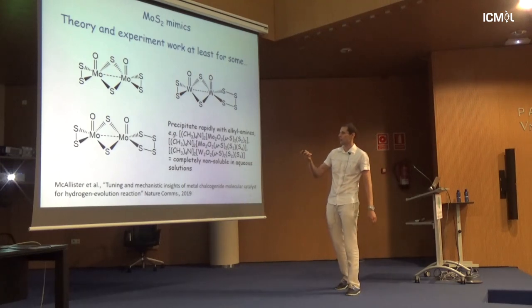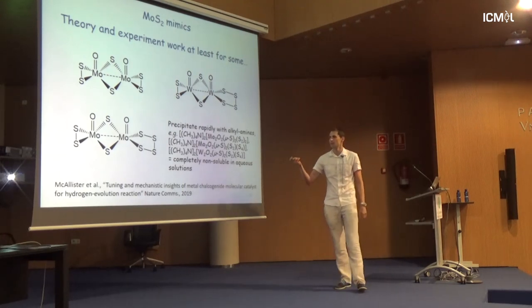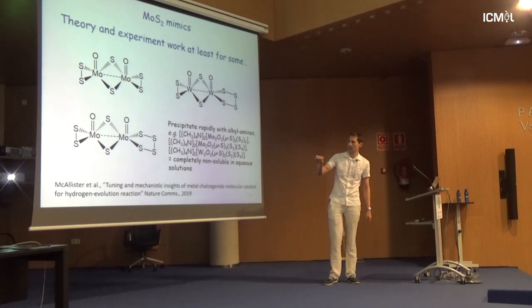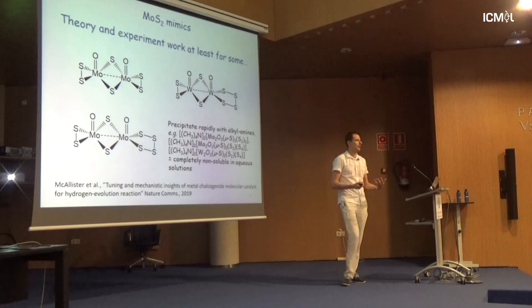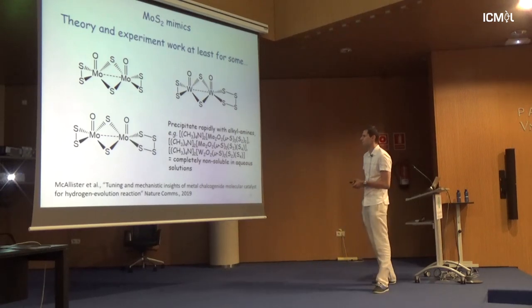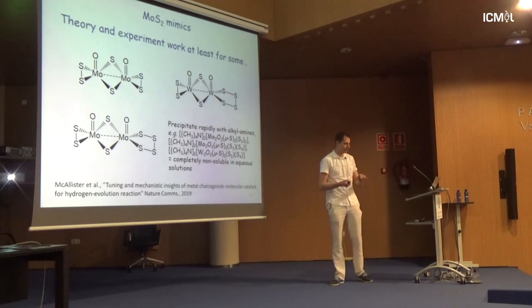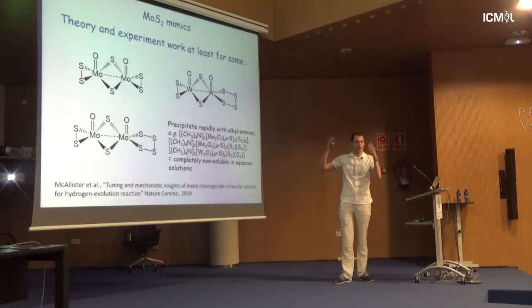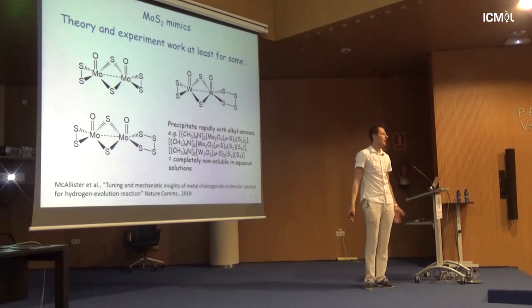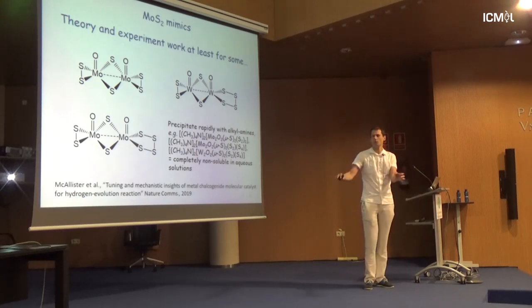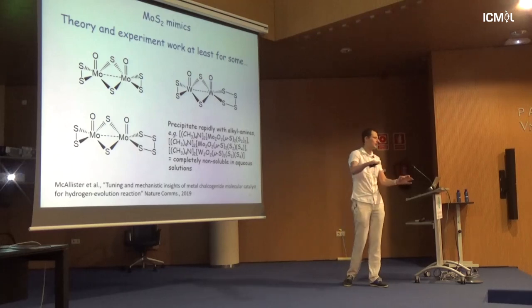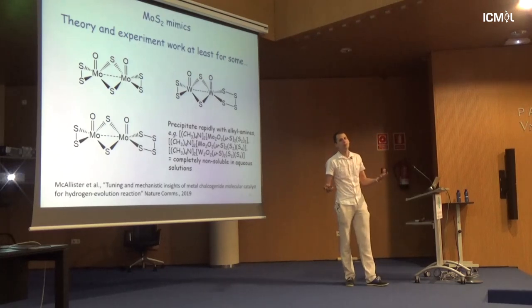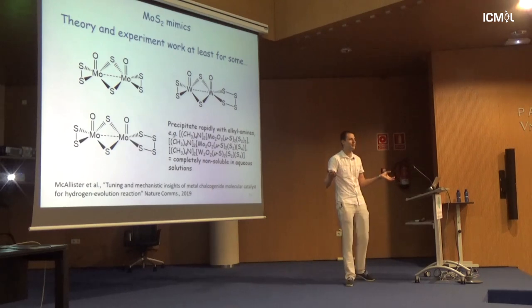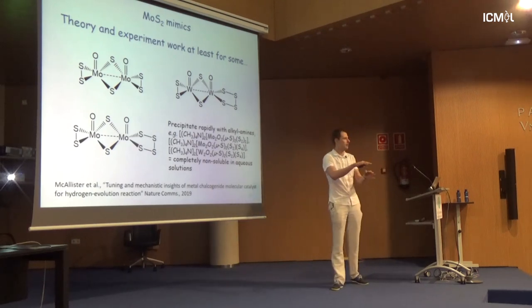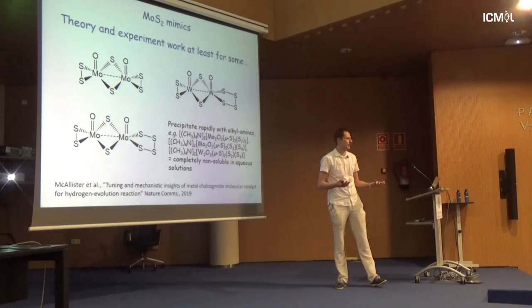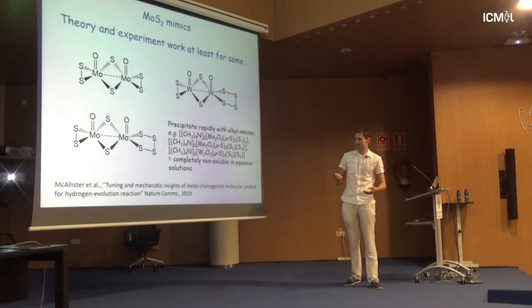Still very interesting, three model compounds. All three of them have this edge, so we can really try and compare and see what's going to happen. What is great about these molecular materials is that you can precipitate them very, very quickly, and we can make them on electrodes. We make fantastic films, well, not fantastic by thin film standards, so they're not smooth, but they just grow. It's a sort of self-assembly on our electrodes, so you can test them very easily.